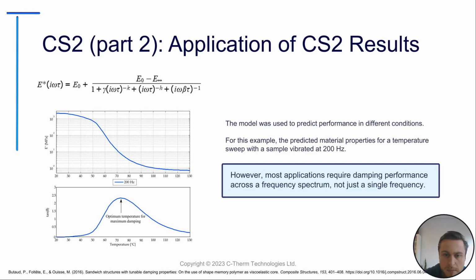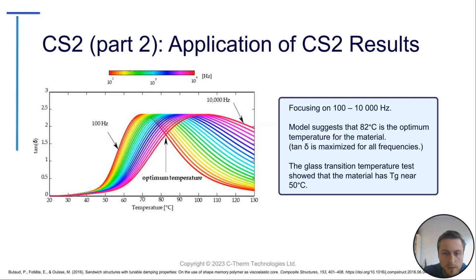However, most applications require damping performance across a frequency spectrum, not just a single frequency. This is what I thought was really interesting and innovative about what they did. They modeled the performance with temperature ramp tests from 100 hertz up to 10,000 hertz. They were able to get this really nice looking curve, and identify at what temperature you would have the maximum damping to absorb all that vibration. So the model determined that the optimum temperature was 82 degrees Celsius, marked by the arrow here, because that was where tan delta was the highest for each curve.